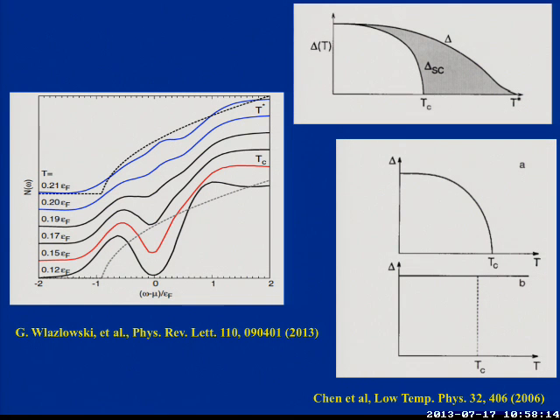If you look at the density of states as a function of temperature, this is energy and this is density of states. At zero temperature, they look like this. This is not zero temperature, it's 0.12. Red is the critical temperature, so you see a big dip. If you had a normal Fermi gas, it would be like the dashed line, which you observe only at relatively high temperatures.